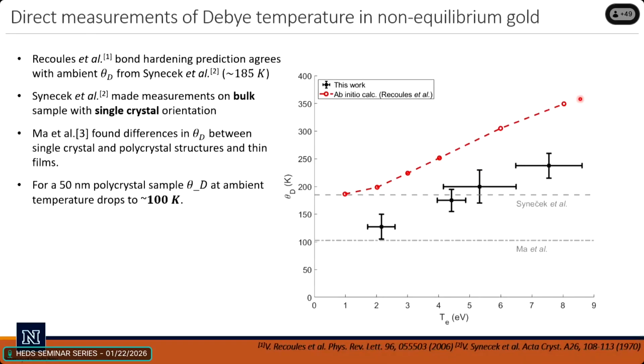And so we can look up the Debye temperature for polycrystalline gold, which is what we have, and it goes right here. This is our suggestion of the starting point for our measurement. And then we see bond strength increases afterwards.